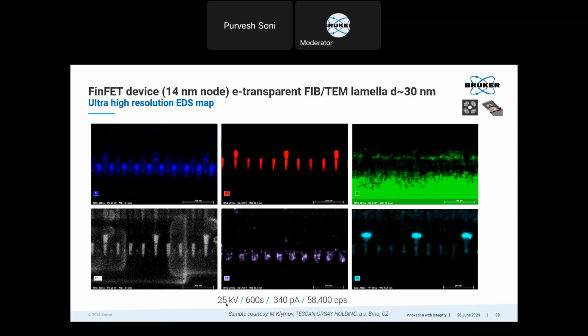And this was acquired at 25 kV and low probe current, around 300 picoamperes, and still I could get 58,000 counts per second for a 30 nanometer thick lamella, which, if you work with these kind of materials, you know how poor the signal is if you are working with EDS and STEM in SEM.